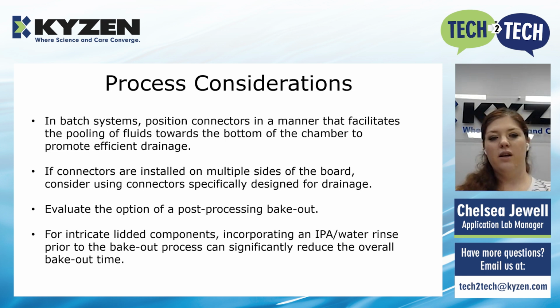We mentioned earlier for those lidded components that it's very easy to get fluid into those, and somewhat more difficult to fully dry them out. So what we've implemented occasionally is an IPA water rinse prior to a bakeout process. What that's doing is allowing the IPA water combination to displace your rinse fluid and then promote drying once you go into a bakeout process. It will reduce the overall bakeout time because you're not just focusing on the water in a very closed off environment. Typically, we're looking at a bakeout that's more in the hour range than the multi-hour range. And that can be implemented not just for lidded components, but for large packages where you're seeing water pooling underneath. That IPA can help displace some of those materials and help with drying.